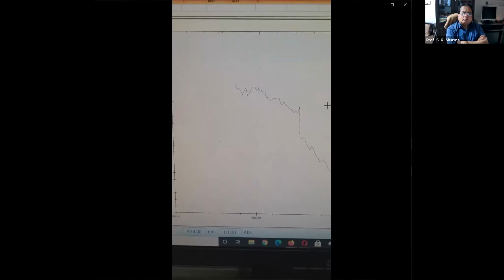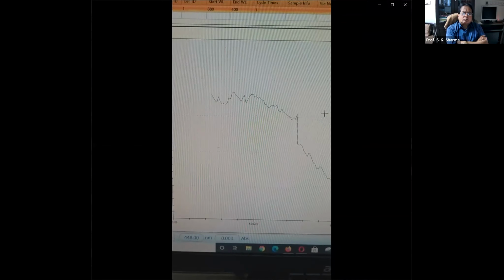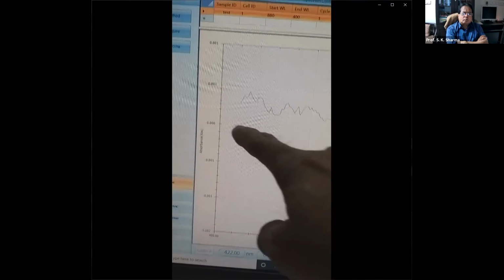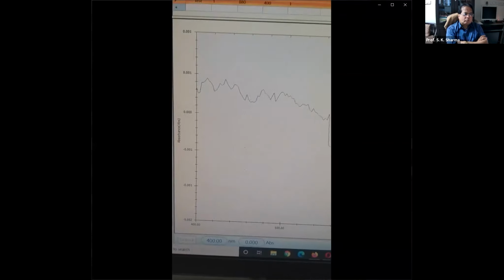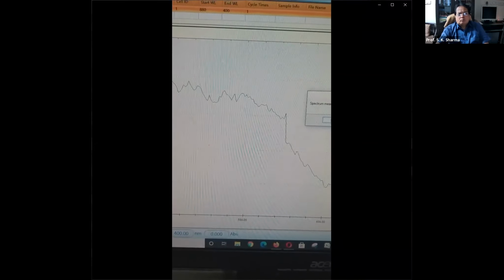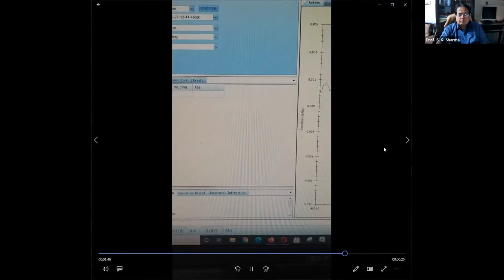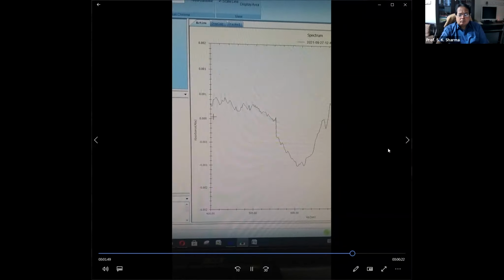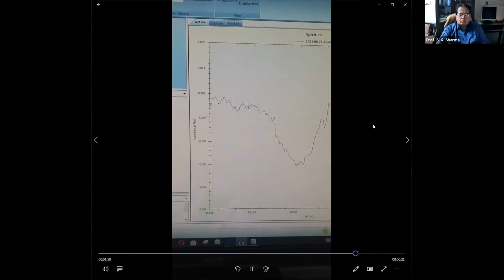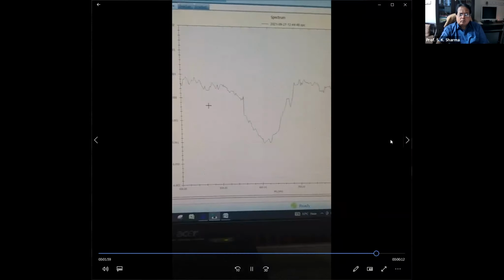So the peaks which you are looking at are around the zero line. Zero line is this line. So this is around 0. Okay, so it means there is a minor, random absorption of around 0.001 or of that particular order. So it means that the reference and the standard sample cuvettes are nearly the same.